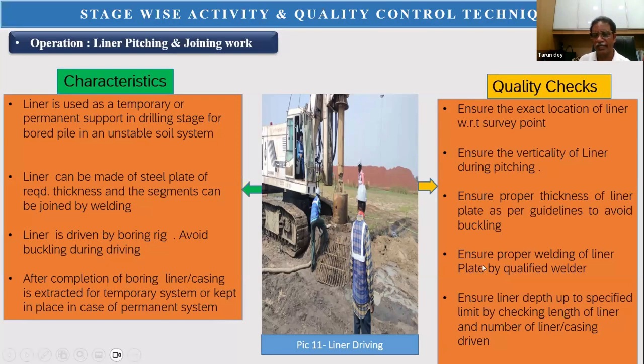And then for proper welding of the plate, you need to have qualified tested welders, as well as your welding procedure needs to be verified before you start the welding. So we have a systematic process to qualify the welding procedure through making a test plate. That is to be done first before we go for the full scale welding. And ensure the length of the liners, up to which depth it is driven, that should be recorded.